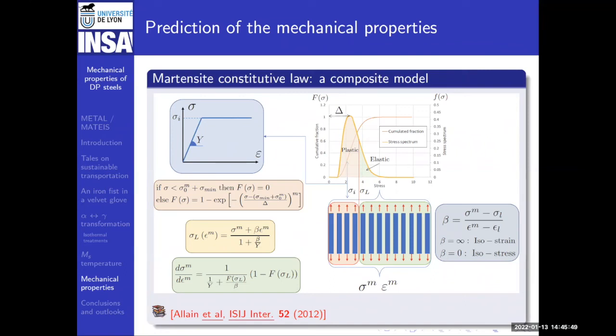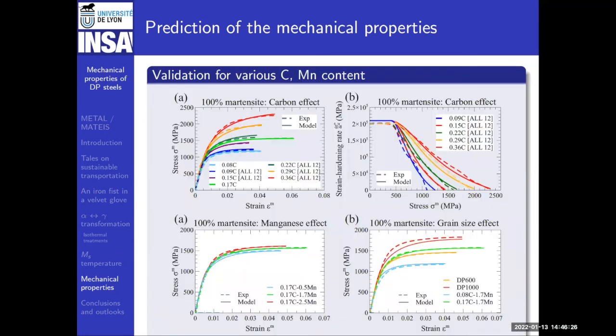You know that martensites are needles. Some of them are very tiny, some of them are larger, and the local yield stress of one needle depends on its size. So you can assume that it's distributed like that. And if you combine with a law of mixture that is in between isostrain and isostress, you can end up with an evolution equation that gives you the mechanical property of martensite. We don't have to enter into the details of these equations, but what is interesting is to know on which basis it's built. And then, once again, for fully martensitic steel, depending for example on carbon content, manganese content, and grain size, we end up with a model that works quite well. And now we combine the two.